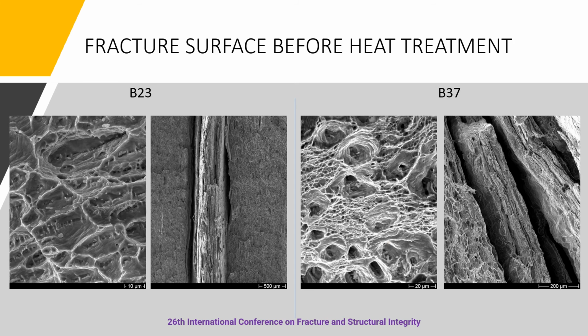Coming to the fracture surface following the tensile test, before heat treatment, it can be seen that both the alloys B23 and B37 show a similar kind of ductile fracture. There is also the presence of delamination layers that highlight the presence of defects during the rolling process of the material.